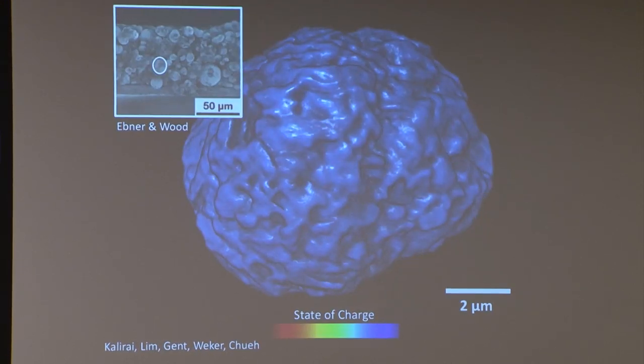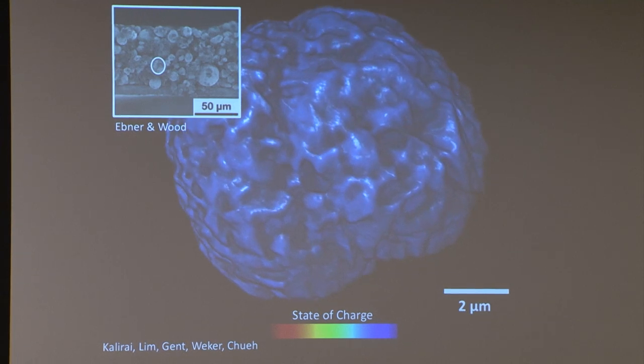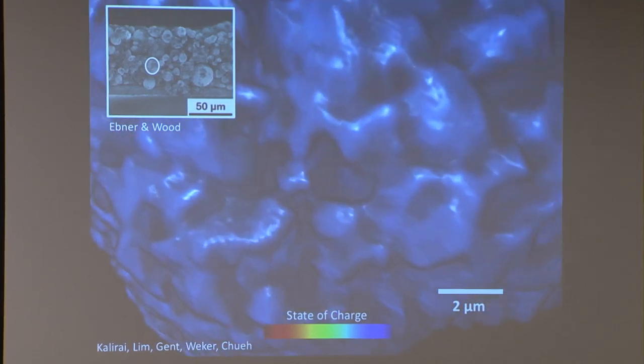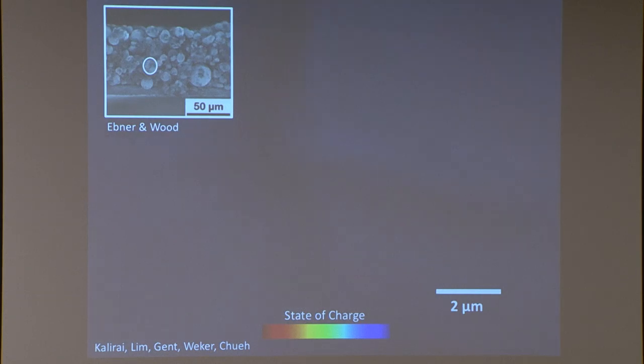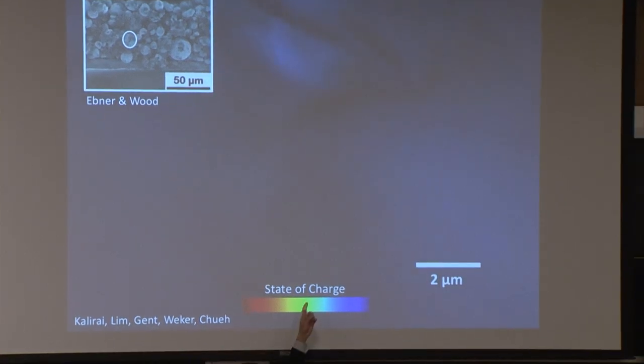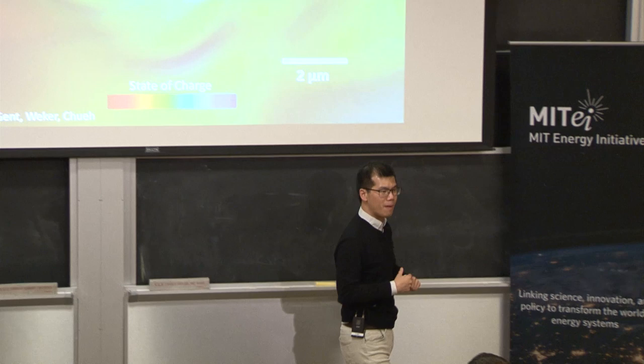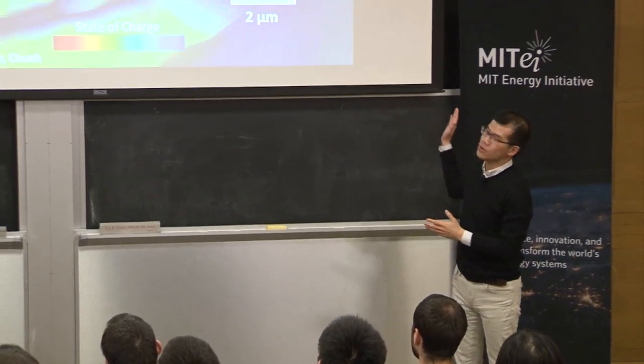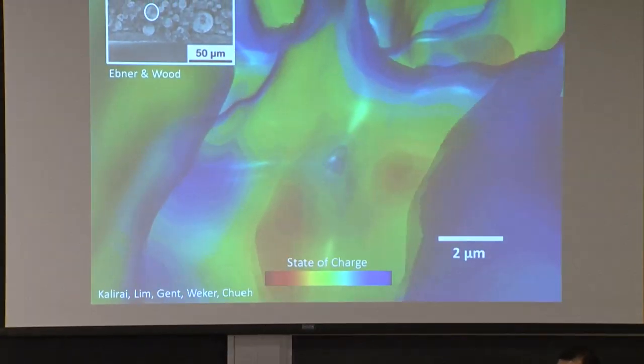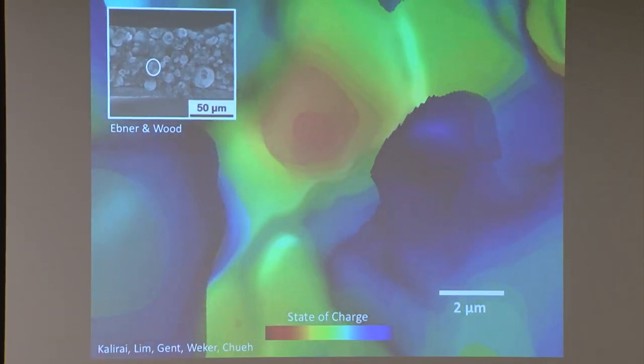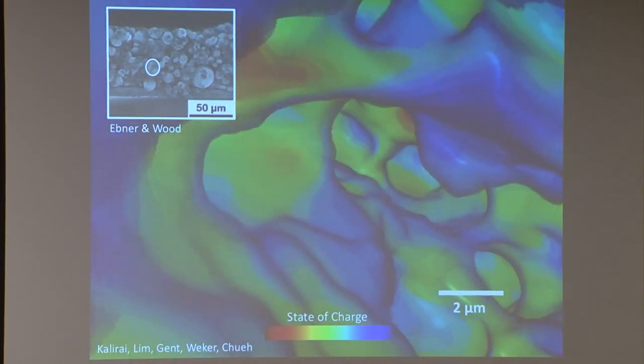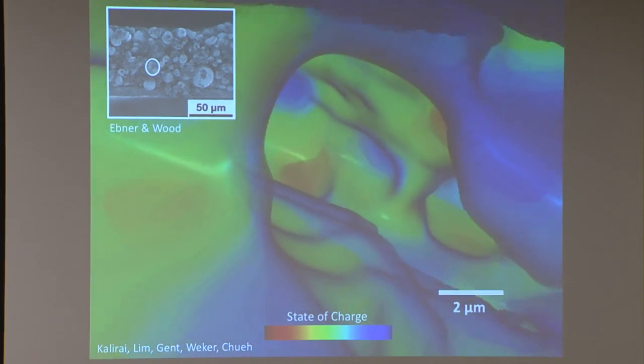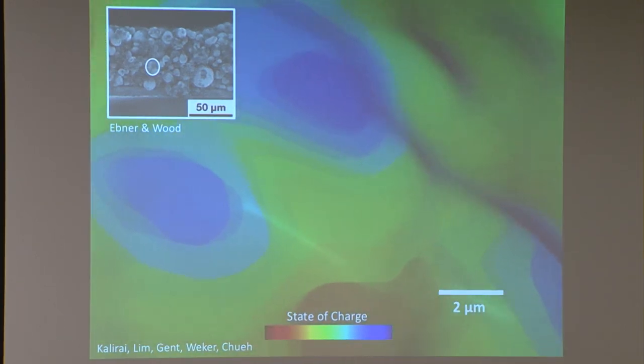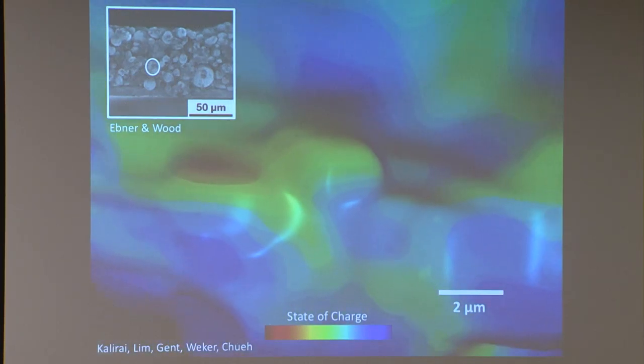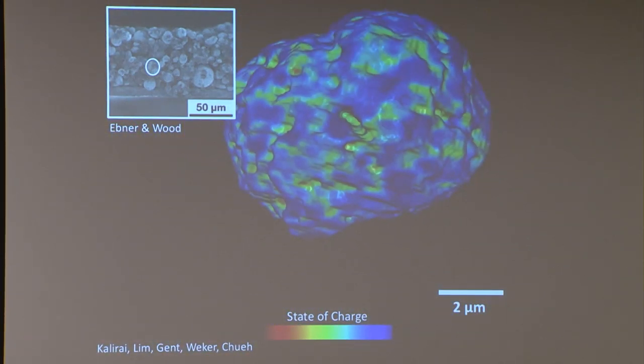Then you look into one of these battery electrodes. This is the schematic of the picture here on the top left. That's a cross section. And each one of these particles you see consists of these particles. They're about 10 microns in size. And the colors you're seeing are the mapping of lithium distribution in this material. So we went from 10 centimeters down to a few microns, and then again being able to characterize the heterogeneous behavior of this material. You can see all these spots. This is where the lithium is residing in this material as you charge and discharge the battery.